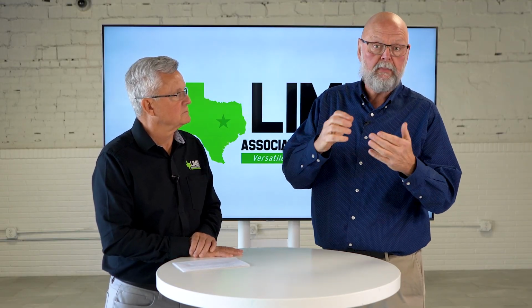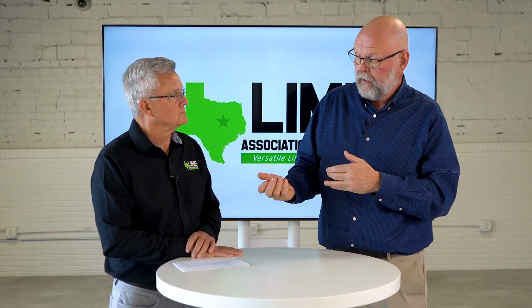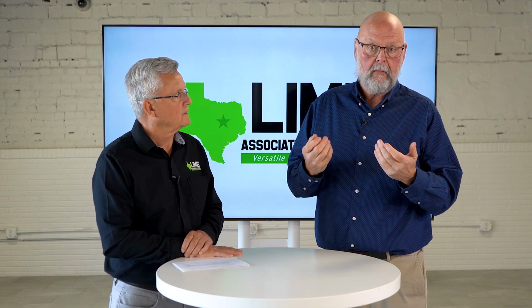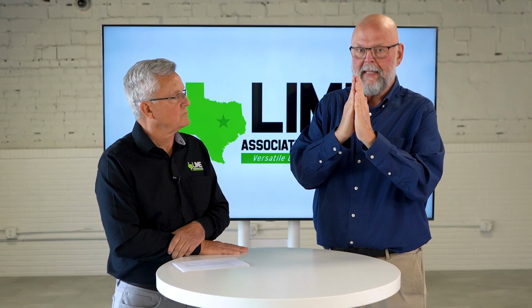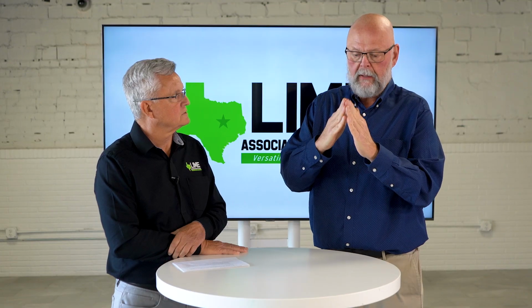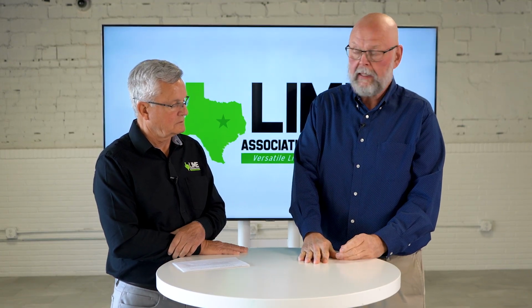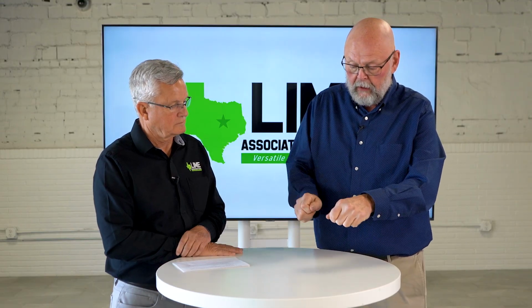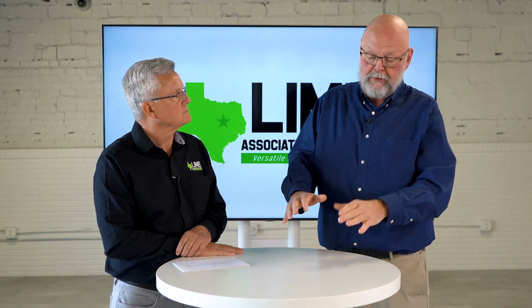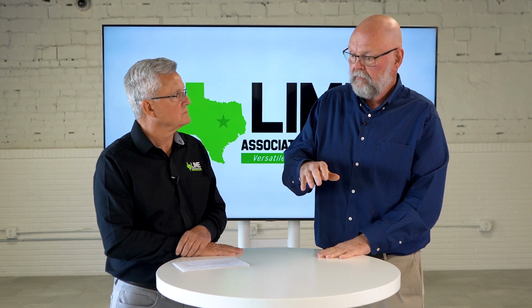So the first step: lime, being calcium oxide, converts to calcium hydroxide for soil calcium. It comes in, it immediately starts dissolving in the water, you start to mix it in, and all of a sudden it goes to the surfaces. It kicks off sodium, it makes that layer a little bit thinner, and instead of being face to face, now it can go edge to face. So you actually start making a house of cards. You have a deck of cards, you stand them up, they're going to fall down. If you're good enough, you can take cards and build them at angles and actually make a several-story house out of it. That's what immediately happens, that immediate textural change.